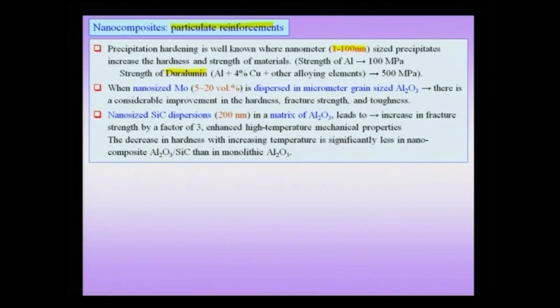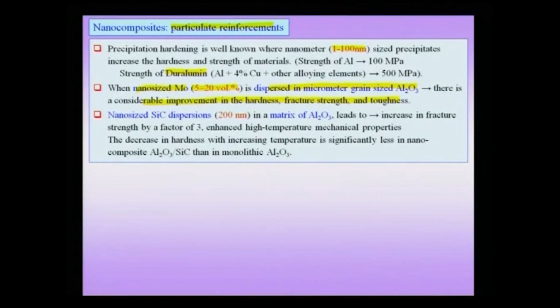But we will take up other examples like nano sized molybdenum in a volume fraction of about 5 to 20%, which is from the usual small volume fraction to a reasonable volume fraction. When it is dispersed in micrometer grain sized alumina, that means the grain size of alumina is no longer in the nanoscale, it is only the molybdenum reinforcement which is in the nanoscale. There is considerable improvement in hardness, fracture strength and toughness.